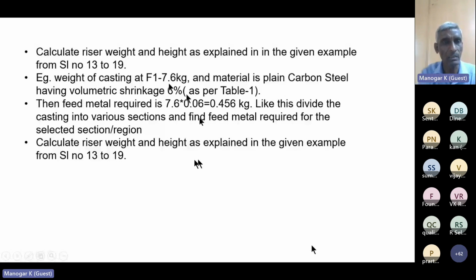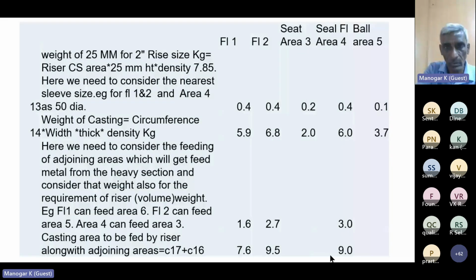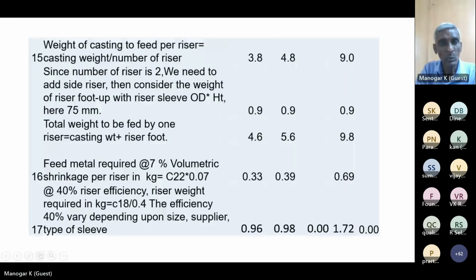So for the weight of the riser, I take 25 mm as a guideline so that I can arrive at the height. The weight we want to feed is 5.9 kgs. For that, volumetric shrinkage is taken as 6%. Weight of the casting to feed per riser is 3.8 kgs. Since the number of risers is 2, we need to add the side riser, then consider the weight of the riser foot, and that is 0.9. Total weight to be fed by one riser is 4.6 kgs.